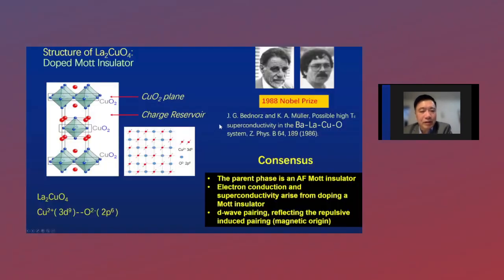So we know that cuprate was found in 1986, and in 1988, very quickly, the Nobel Prize was issued to Bednorz and Müller. The typical structure for the cuprate is this copper-oxygen plane. We know that this is the major player for superconductivity, and between them there is a charge reservoir layer. After so many years of study, nowadays I can probably conclude some consensus. For example, the parent phase is an antiferromagnetic Mott insulator, and the electron conduction and the superconductivity arise from doping a Mott insulator. And I personally believe that the d-wave pairing has been proved, which reflects repulsion-induced pairing. So it must most likely be of magnetic origin. Otherwise, we cannot get this repulsion-induced pairing.